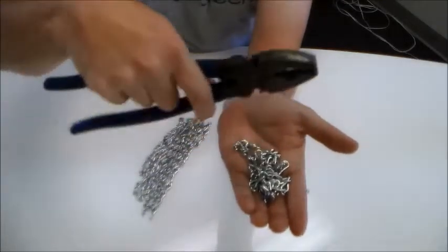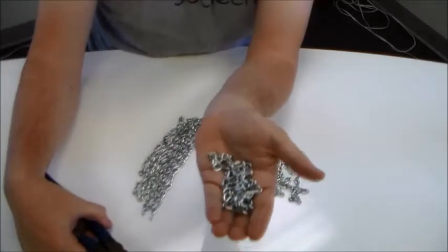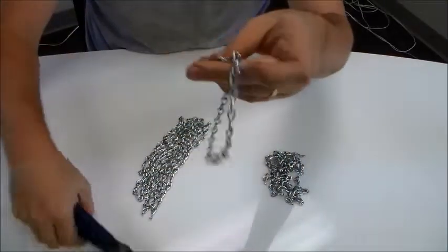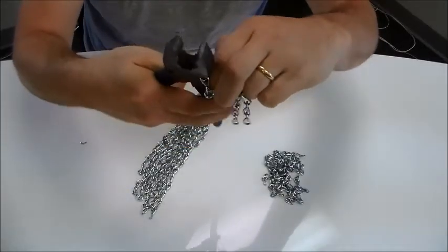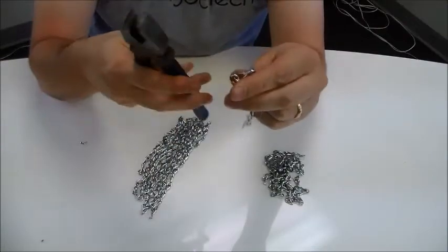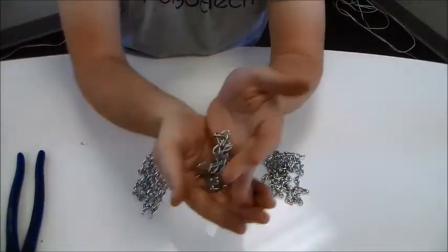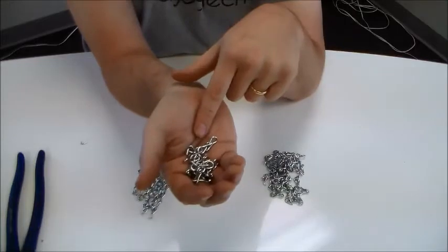The first sign of polymer degradation is simply the reduction of molecular weight — a process called random chain scission. That simply means water is breaking the polymer randomly throughout the matrix. At first the polymer looks and feels the same. It's only after this happens several iterations, with repeated breaking producing shorter and shorter chains, that eventually instead of chains of polylactide, you end up with just the lactic acid itself.